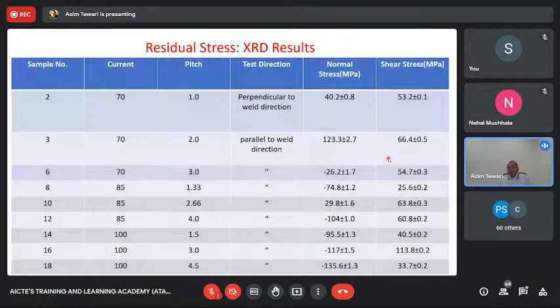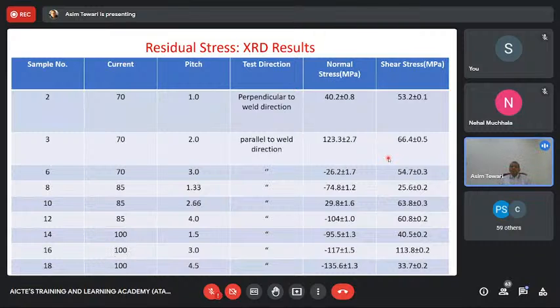But what is most important is what I just wanted to bring out to you, which is these residual stresses. Now you can measure the residual stresses by X-ray diffraction. And there are many other ways in which you can measure residual stresses. So when you are doing additive manufacturing, the part may look very nice and good, but it will have residual stresses. And you need to measure those residual stresses.